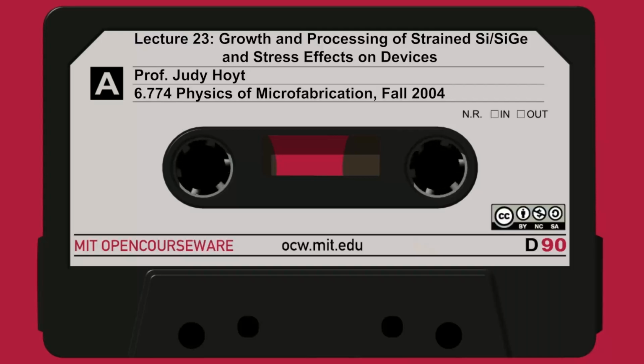Well, it doesn't sound too bad, but if you just look at some of the diffusion coefficients, in fact, these different lines are measured. This is the germanium self-diffusion in silicon germanium alloys for different germanium content. So this is for silicon, so this will be silicon self-diffusion. This is 10% germanium, 20%, 30, 40, and 50. So if you just look at a given temperature, say at 950 degrees, look at what's happening to the diffusion coefficient. In silicon germanium, the diffusion is very slow for a low germanium content, here at around 10 to the minus 17th centimeter squared per second. But if you go up to a 40% alloy, the diffusivity goes up by 2 orders of magnitude.